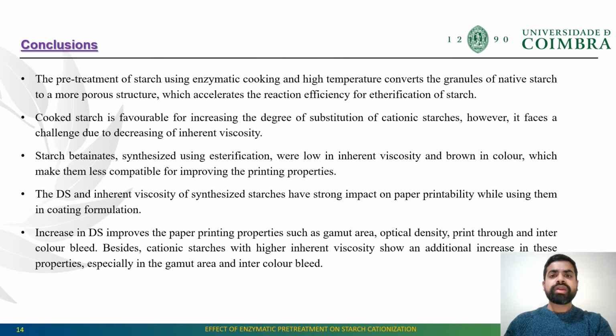Finally, it can be concluded that the pre-treatment of starch using enzymatic cooking and high temperature converts the granules of native starch to a more porous structure, which also accelerates the reaction efficiency of etherification of starch. While the cooked starch is favorable for increasing the degree of substitution of cationic starches, it faces a challenge due to the decrease of inherent viscosity. In contrast to etherification, starch betainates synthesized using esterification were low in inherent viscosity, and their brown color makes them less compatible for applications such as paper coating for improving printability.